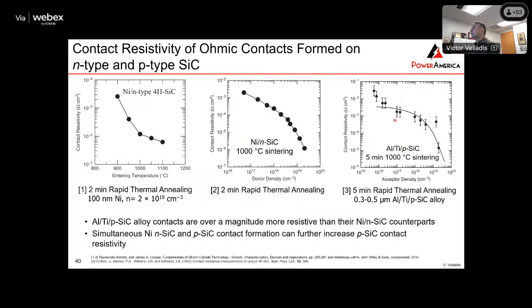And you can see here that in the case of the P-type, even for high doping densities, you're at 10 to the -5 or so. So you're an order of magnitude more resistive compared to the N silicon carbide contact. So when you're doing both N and P silicon carbide contacts, you typically put nickel down, and that makes things even worse because you're not using the optimal aluminum alloy for the P+.